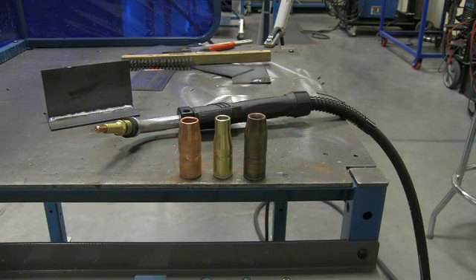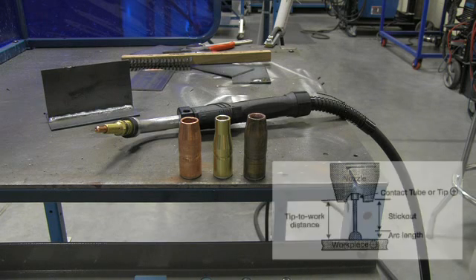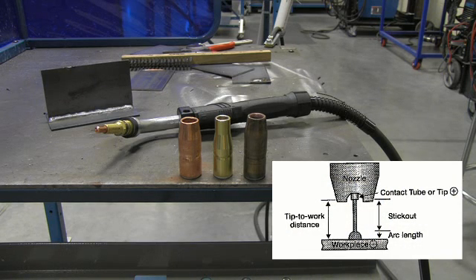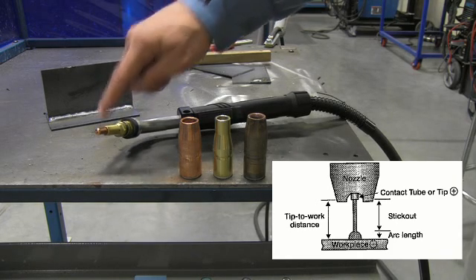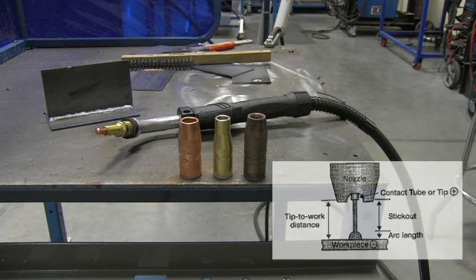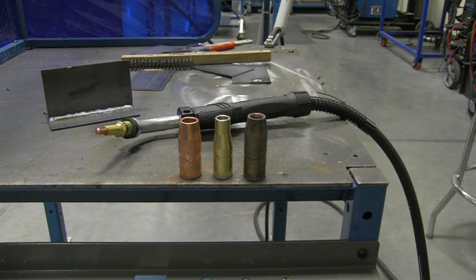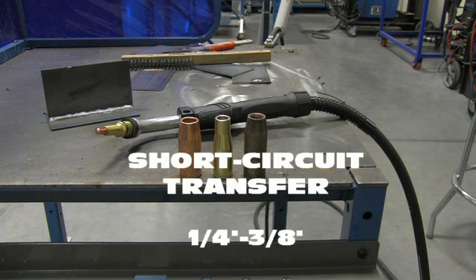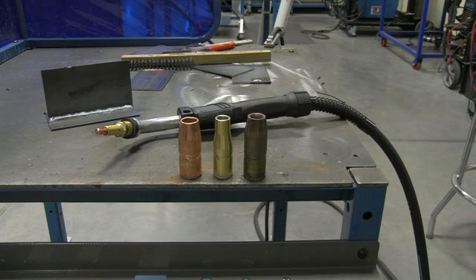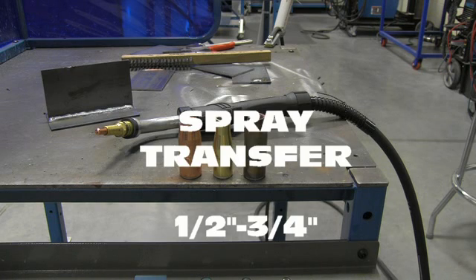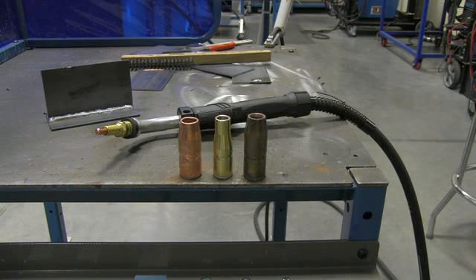So before we start welding, we need to discuss one more welding parameter or welding variable, and that's your electrode extension. The electrode extension is the distance from the end of the contact tip to the welding arc, to the actual arc. Okay, for short circuit welding, it's important to maintain a 1/4 to 3/8 inch electrical stickout. For spray transfer, a 1/2 inch to 3/4 inch is mostly recommended.